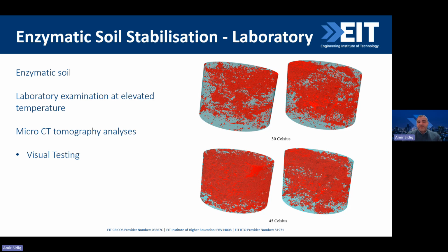And then for 45 degrees, you can see because it's an expansive material, the shrinkage is happening in this case. So there's a lot of void happening within the raw material. However, for the enzymatic, it's still increasing, but not as much. It's much, much lower compared to the raw material. Now, this is the behavior: during the wetting or during the low temperatures, the void was a bit higher compared to the control, but then at 45 degrees, it's actually controlling it. Now, the shrinkage is not much happening because the enzyme has actually protected this clay material. It's like it provided a coating for this clay material, which limits the shrinkage from occurring.